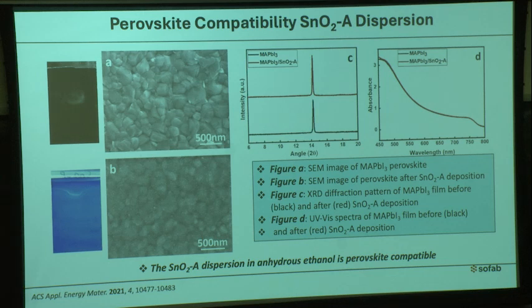If we do XRD of lead iodide, it gives a peak around 12. There is no peak present around 12, and no peak below 14.2. That means this tin oxide is not causing any degradation of the perovskite. That's why it is perovskite compatible.